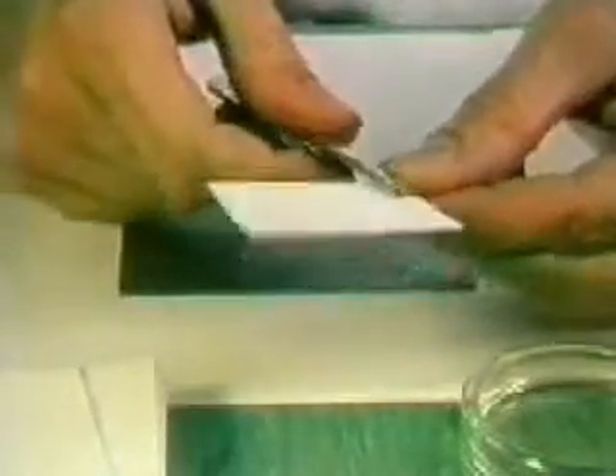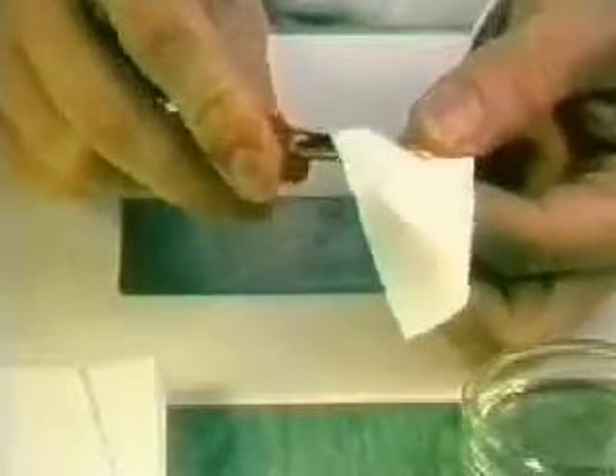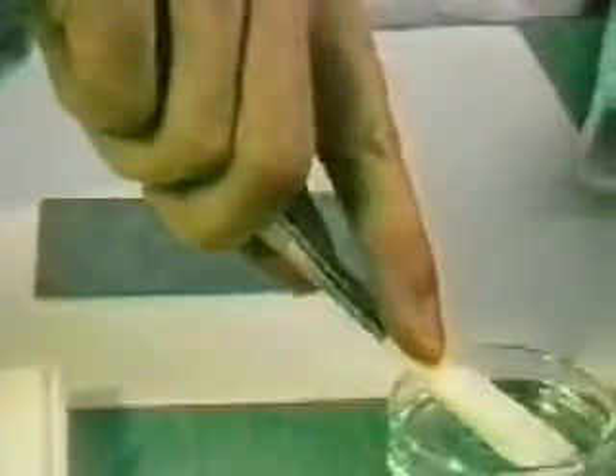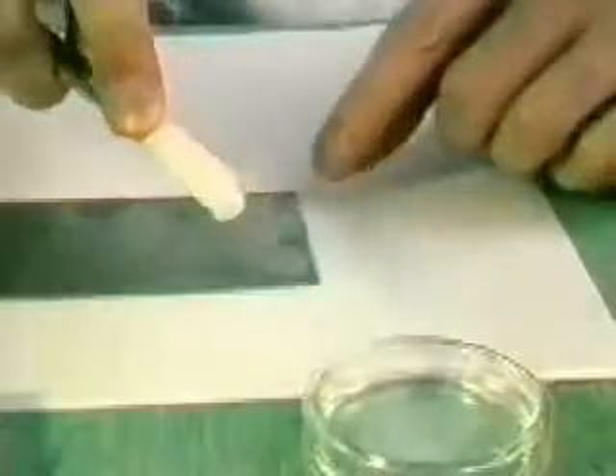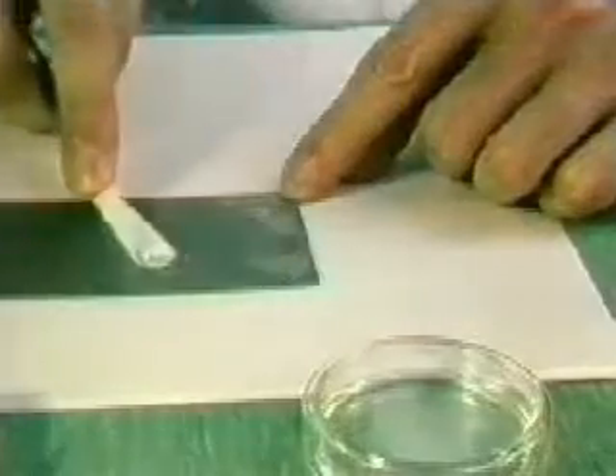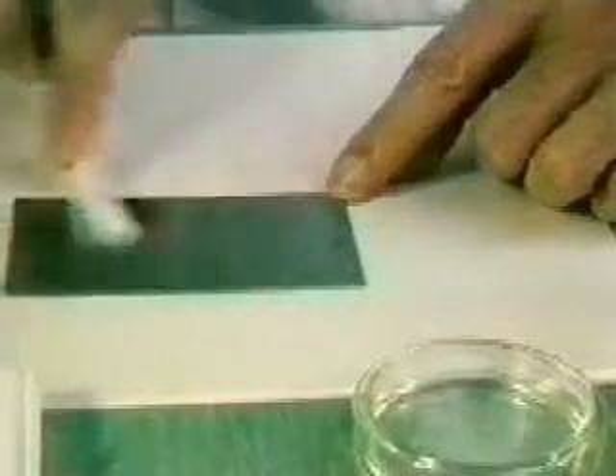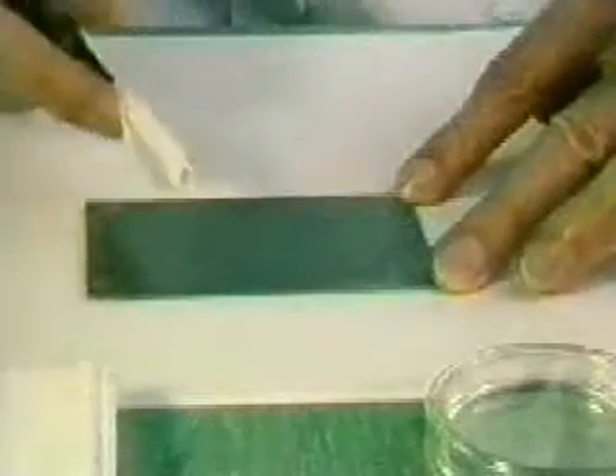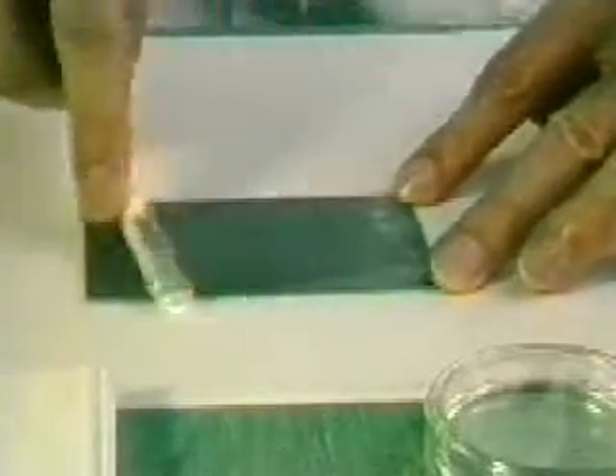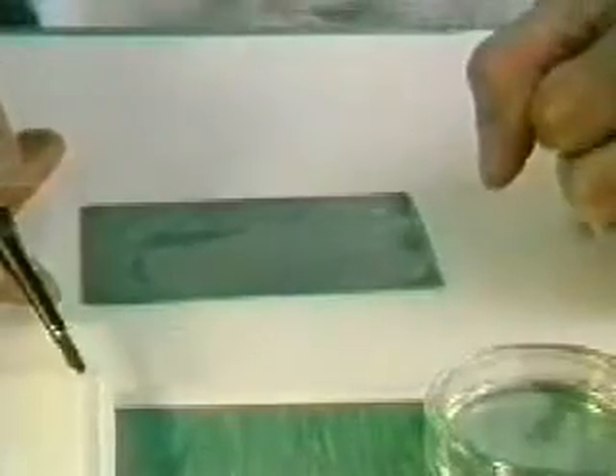The pads cannot be rolled in the direction across the grain. When dipping the pad in the solvent, the fingers must not dip into the liquid, since otherwise the solvent will become unusable due to the grease dissolved from the skin. Each pad should only be dipped into the solvent once, because otherwise it will become unusable.